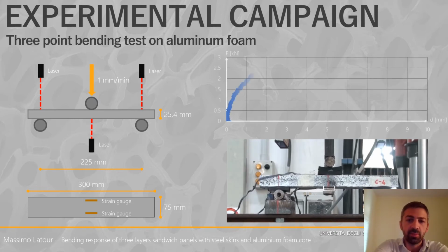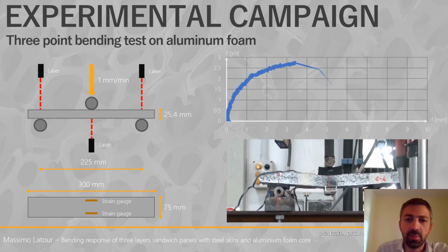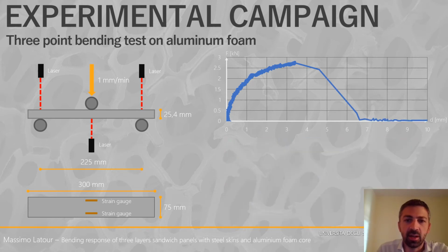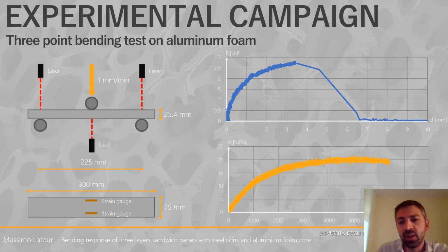In particular, these 3-point bending tests were showing a behavior characterized by the achievement of a yielding point, some strain hardening and ductility up to the failure condition that was achieved due to the failure of the foam at the midspan. The bending stress was shown to be larger than the compressive strength of the material, by a factor of about 2. This is due to the production process, because the panels usually also undergo a lamination after the foaming. Therefore, these materials typically have very large resistance in bending, larger than in compression.